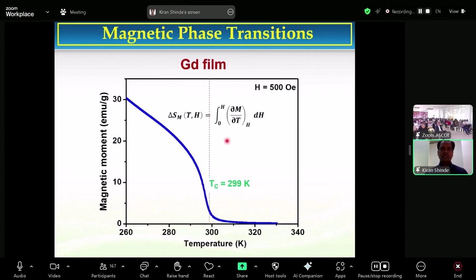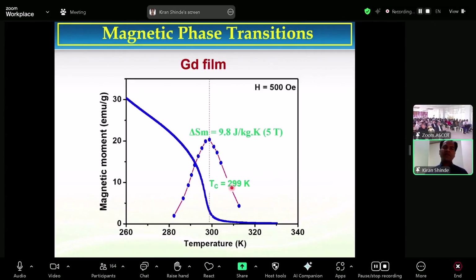So as I said, this equation we have to use for the measurement of magnetocaloric property, delta Sm. So the magnetic entropy change is maximum around the Curie temperature. So in this temperature range, we can use this gadolinium film for the application purpose. So delta T, or change in temperature, in this gadolinium case, is 2 Kelvin per Tesla. So if we use the 5 Tesla magnetic field, we can get 10 Kelvin change in temperature. So 10 Kelvin is good enough to cool the room temperature for the application purpose. In this case, the maximum entropy change observed is equal to 9.8 joule per kilogram per Kelvin when we apply the 5 Tesla external magnetic field.